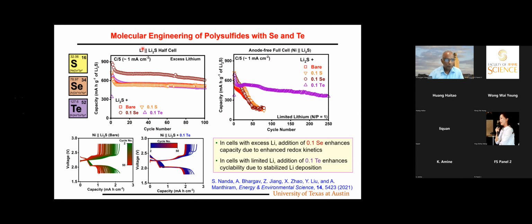This is a cell where we have excess lithium on the anode. Because the selenium addition helps to have better redox, which helps to increase the conductivity, and it also helps the redox reaction, so capacity is increased. If you go to the anode-free cell, the same four things, if you look, only tellurium addition maintains good cycle life. The others have poor cycle life, because here the lithium is limited.